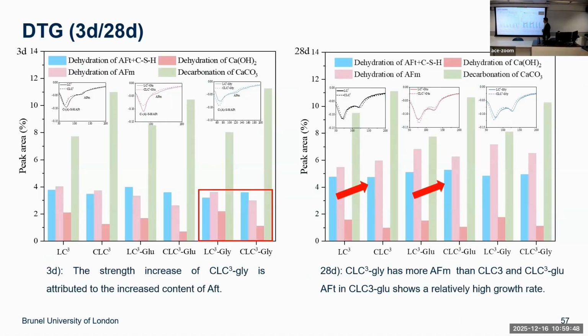And the DTG result helps quantify how much carbon dioxide will be sequestrated. We are doing this at 3 days and 28 days. At 28 days, carbonated LC3 with glycine or glutamic has more AFm than the one without glycine or glutamic. And AFt in the carbonated LC3 with glutamic shows a relatively greater growth rate.